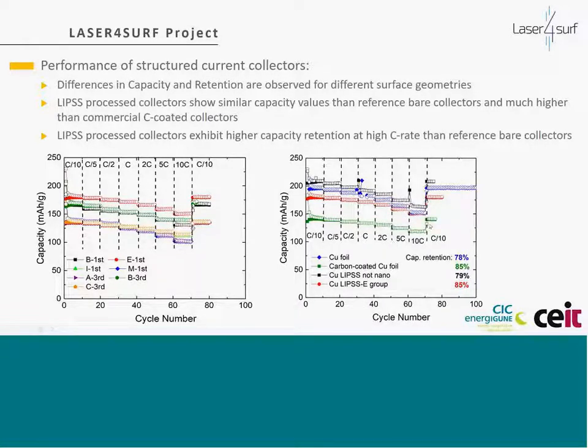And if we compare the behavior of the best of the conditions we have obtained with the standard for cell manufacturing, we can see here this is just the copper foil, a standard copper foil without any modification and without any carbon coating on top of it. Then we have the green one, which corresponds to the copper foil with the carbon coating. That will be, let's say, the standard for battery manufacturing. And then we have the sample we have obtained to behave the best, and also another reference for the same material we have used for the current collector.